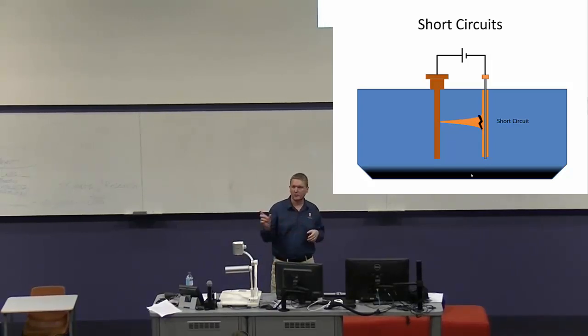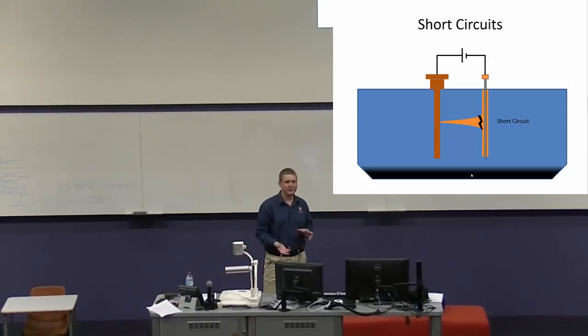Even with that backup plan, every now and then you still get shorts. In that case, we have a team working 24 hours around the clock. They walk over the top of sections with special gauss meters, detect high current flows indicating a short, then shove a big steel blade down between the plates to knock the short off, and it falls to the bottom of the cell. We have about 1,000 cells spread across 37 sections, and they knock off around 3,000 to 4,000 shorts per day, making sure every electron pumped through is producing copper.